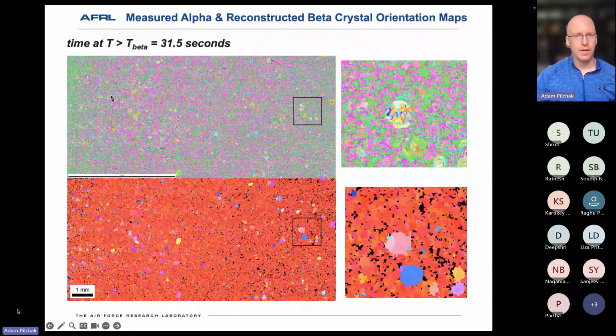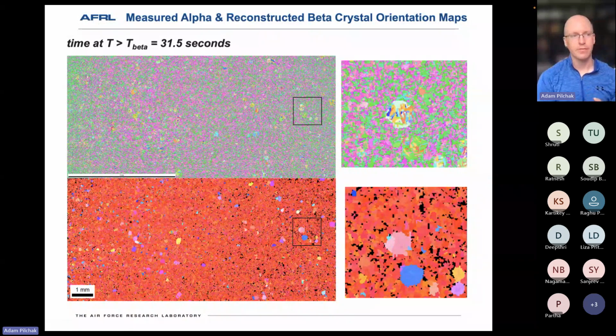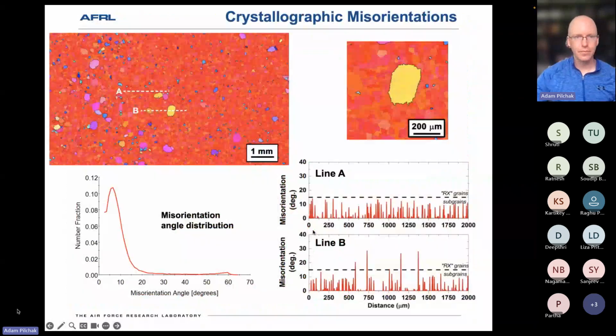This was, again, the example of one after 30 seconds, and you'll recognize that a lot of these green and purple orientations are very similar to what we saw in that fine-grained halo earlier. But in some locations, you do see evidence of different alpha phase orientations. And so these are so-called recrystallized grains. The reconstructed beta map is on the bottom, and then the corresponding area here, you can see that indeed they are highly misoriented with respect to the red subgrain matrix.